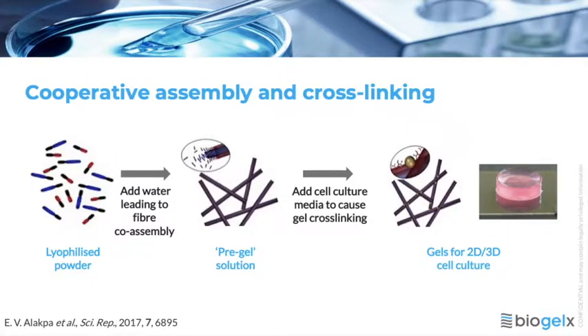The products themselves are shipped as lyophilized powders, so a mixture of these small peptides, and the first step to making your gel with these materials is generally to add deionized water to form this pre-gel solution. The cooperative assembly has already begun at this stage, and we start to get fibre formation of the FF and the S. And then upon addition of a source of calcium ions, so calcium chloride solution or normal cell culture media, which generally contains calcium ions as well, we achieve cross-linking of those nanofibres through coordination of the divalent cation.